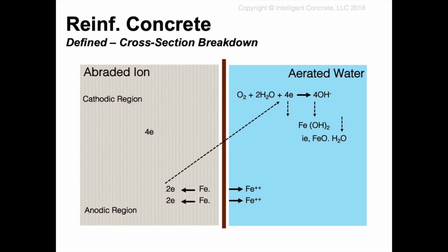The problem is that we're not always in that perfect state, especially when we see these concrete structures that show bleeding. There's something going on here where that passivation layer has broken down, and that reaction that we're going to go through could be summarized with the simple equation of metal plus oxygen yields a hydrated metal oxide. And in our case for wet corrosion, this is a much faster track.